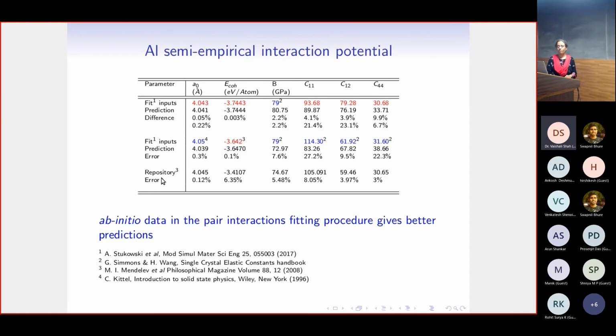The third set of results here compares how our generated pair potential is doing against what has already been generated for aluminum and is available in the repository. So we take the repository potential, and with it we do the predictions for the structure, the energetics and the elastic properties. Then we see that the elastic properties are predicted much better than our prediction. So of course we know we need to improve on this. But between the ab initio and the experimental data, we are seeing that the ab initio predictions come out a little better than the experimental data that we use for the fitting.